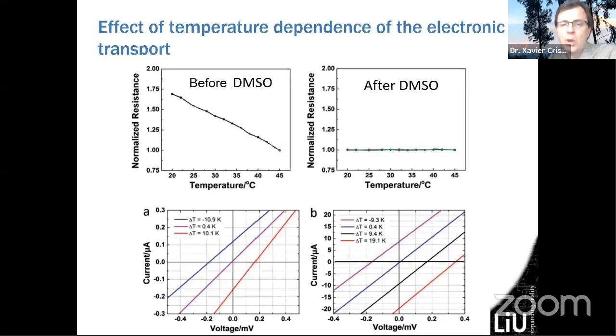That is to say, you're at the crossing between insulating to metallic transition, where the resistance is not depending on temperature - it is independent of temperature. In that case, we get very nice parallel curves here, where we don't apply any pressure but just apply a difference of temperature, and we get very nice parallel lines. So this is an ideal material, because now when you apply a pressure, it will be seen as a change of slope only.